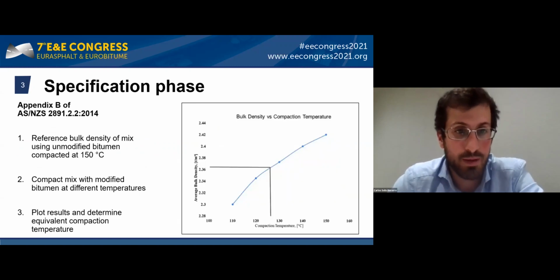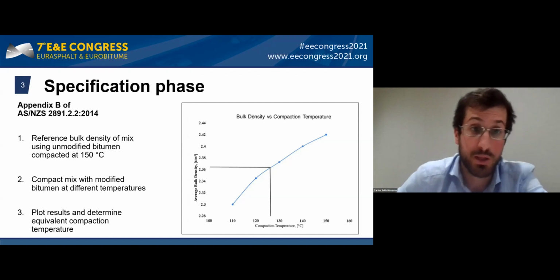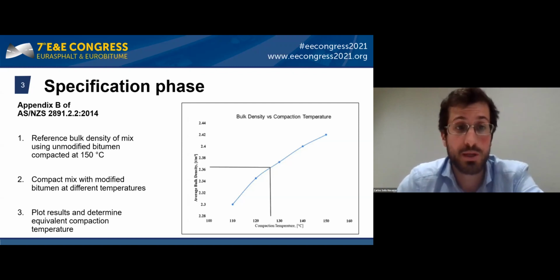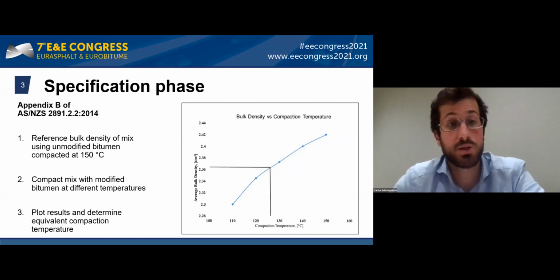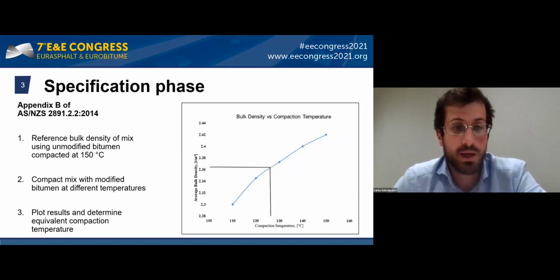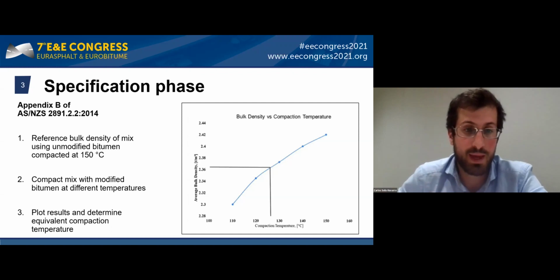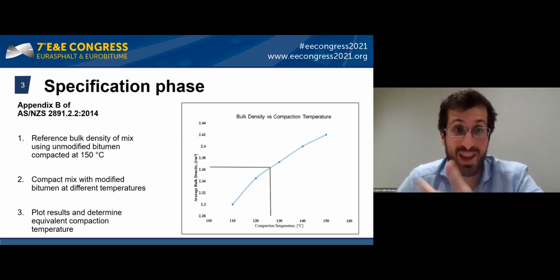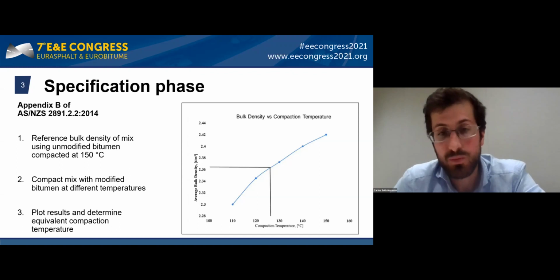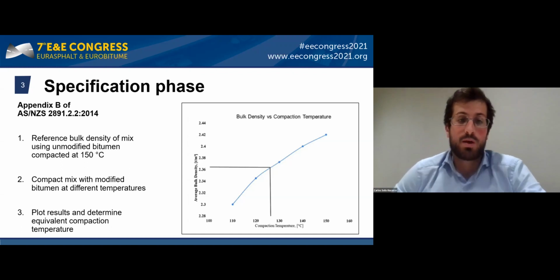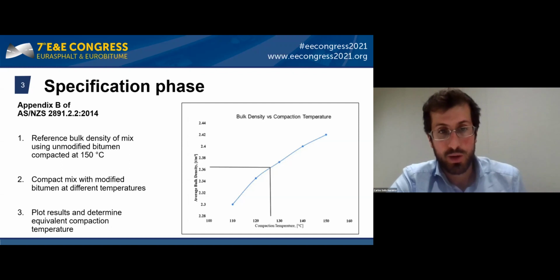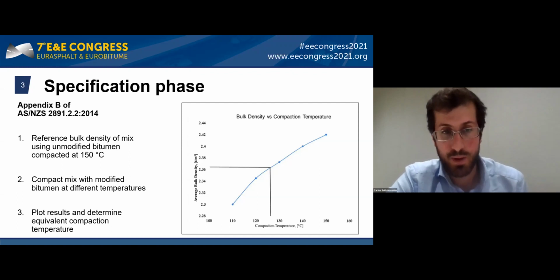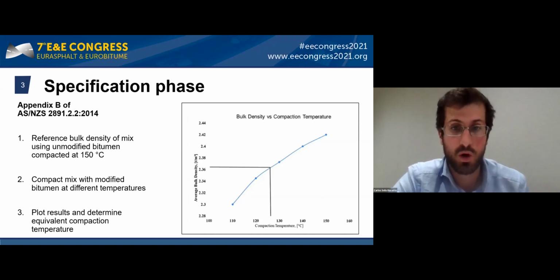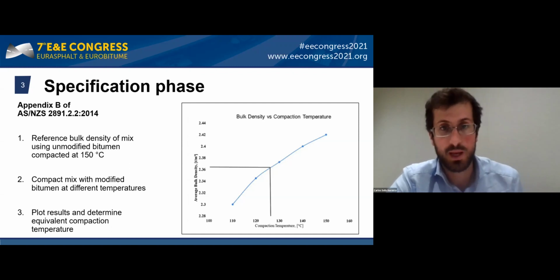In order to calculate an equivalent compaction temperature, the warm mix compaction temperature requires some testing and reporting in accordance with an Australian standard. This is in the case of Australia. The goal here is to get a temperature that will deliver the same performance as the hot mix. For the project where we were not able to get these temperatures, we liaised with the supplier and the contractor, and we undertook all this homework before the delivery date.